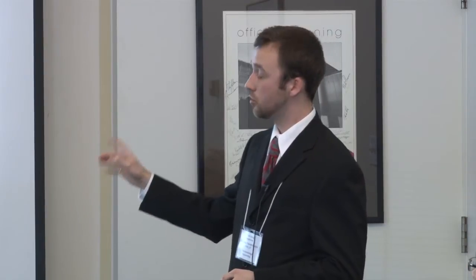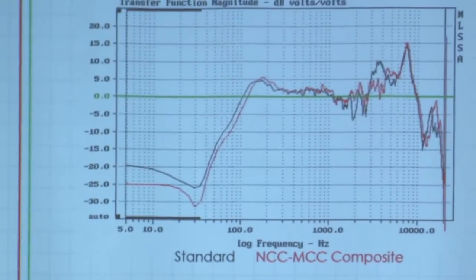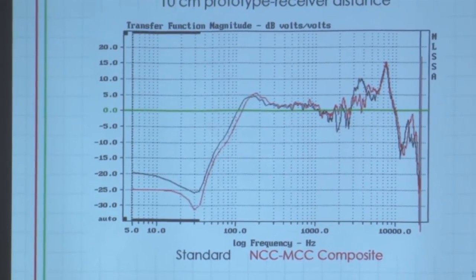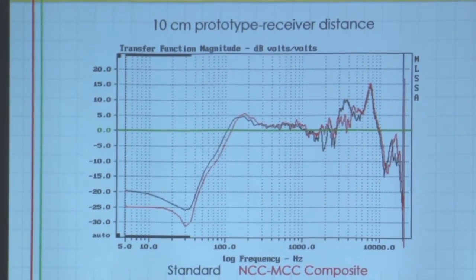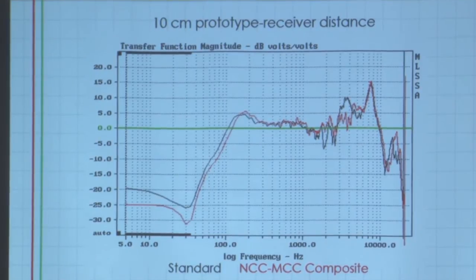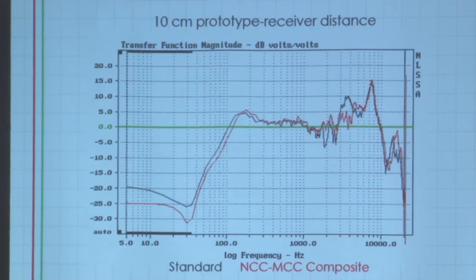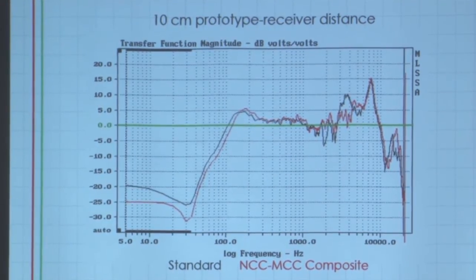When we take a closer look at the data, that is when we place the microphone only 10 centimeters away from the speaker, what we find is that the NCC-MCC composite actually exhibits a flatter response, suggesting that it is even better than the standard when it comes to audiometric performance.